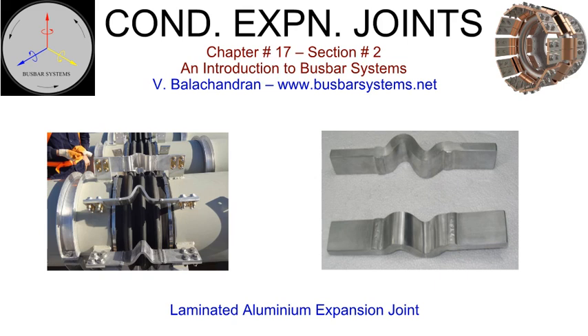If required, tin or silver plating of the aluminium laminated expansion joints at the end tabs is undertaken for bolted expansion joints. This process requires extreme care to prevent any ingress of electrolyte between the shims during the plating process. It may not be possible to wash the electrolyte thoroughly, and the same may surface later, resulting in corrosion and salt formation. The typical cross-section of an aluminium laminated expansion joint installed in a busbar system is 1000 square millimeters or 2 square inches.